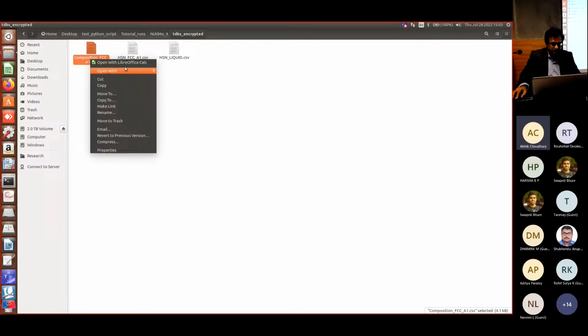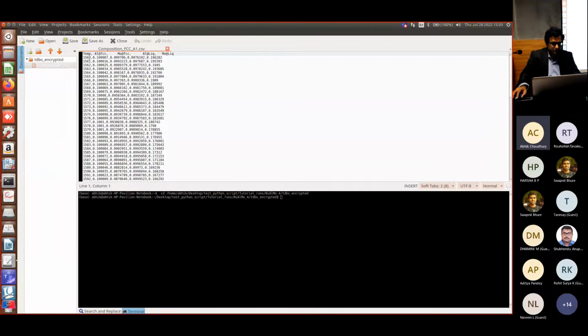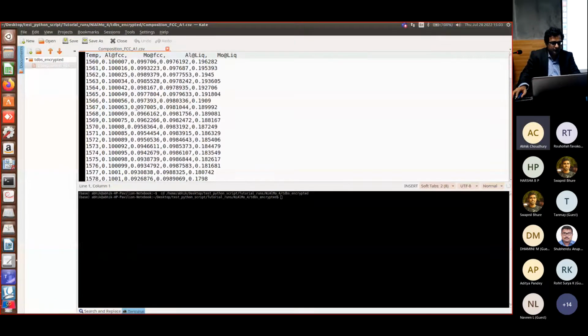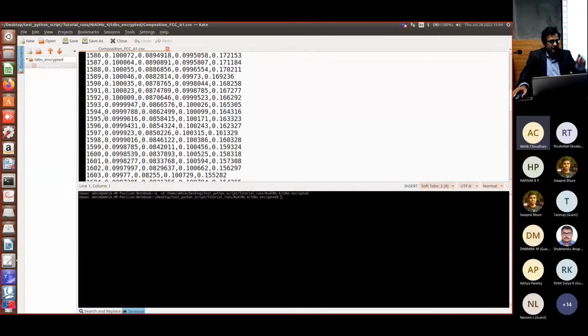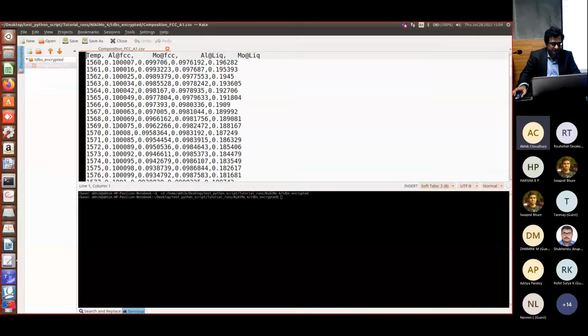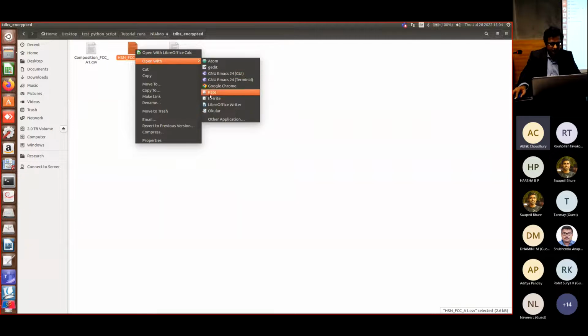So before you run, please check the order of the temperature, because if it's in the inverse order, it's a problem. Remember it's ascending order of temperature, and what you have over here is aluminium, moly, FCC, aluminium, moly, liquid. OK, so how is this done? It is essentially done following the equilibrium solidification path for that alloy composition. So you give an alloy composition and you change the temperature, it will follow the phase coexistence lines, which all have that particular alloy composition in the tie line. So that is how this calculation is being done. And the corresponding extraction is also done for the Hessian.